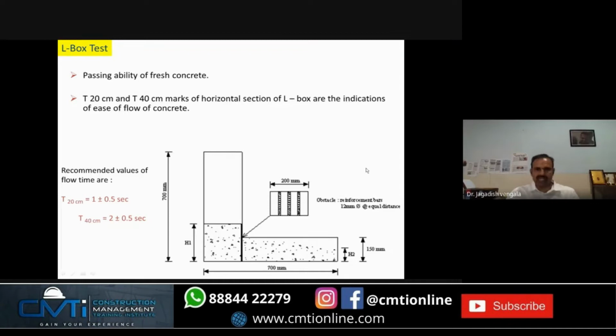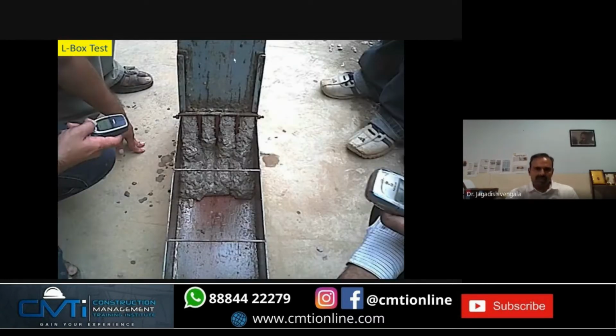There are two boxes, one is a vertical box and one is a horizontal box. You measure the passing ability. You fill the vertical box with the SCC and then lift the gate, and it has to pass through the vertical reinforcement gate that is placed at the center of the vertical and horizontal box. It has to flow through the reinforcement, and you measure various things like time taken to reach 200 mm, time taken to reach 400 mm, and also the height difference H1 by H2, which gives the blocking ratio.